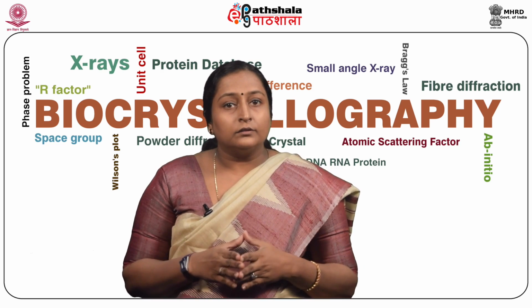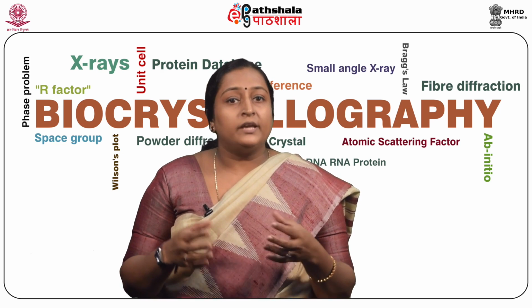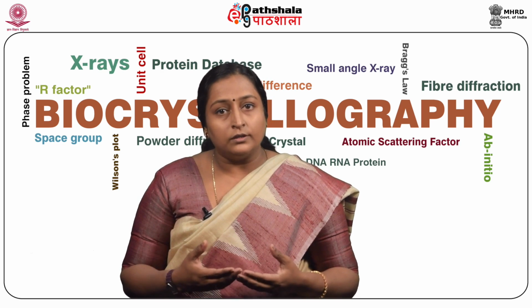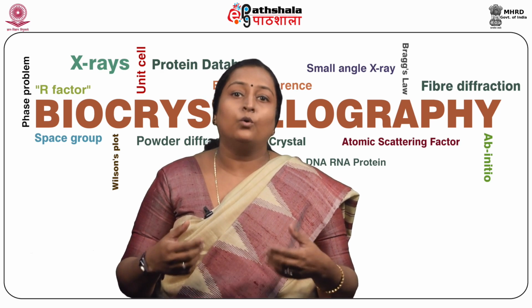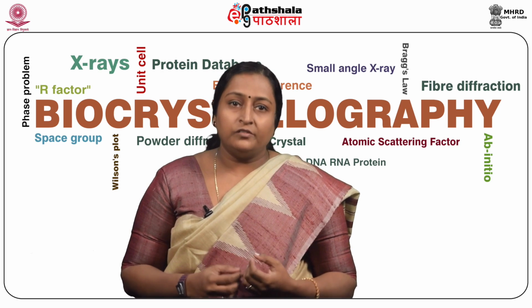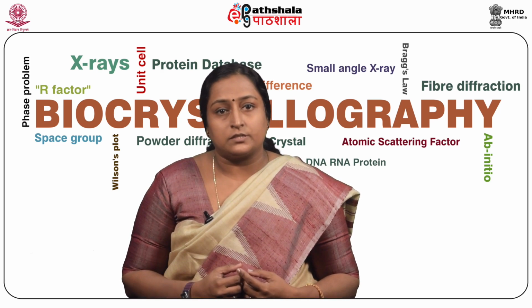Upon comparing the values of R factor and R free, one can actually estimate the quality of the model and the data, and also the extent to which one has overfitted the data. Generally, the R factor and R free differ by approximately 5%.